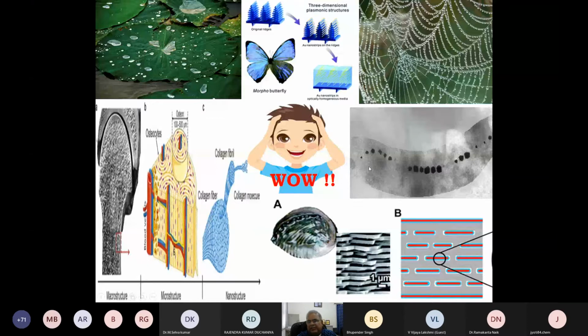There is a magnetotactic bacteria. It is found in some sea beaches. And the beauty of this bacteria is that it has a lipid layer which encapsulates 30 to 35 nanometer magnetite nanoparticles in it. An array of the magnetite nanoparticles is here. And with this array, this bacteria knows the depth and the direction of its swimming. They swim only in a particular direction which is aligned with the magnetic field.